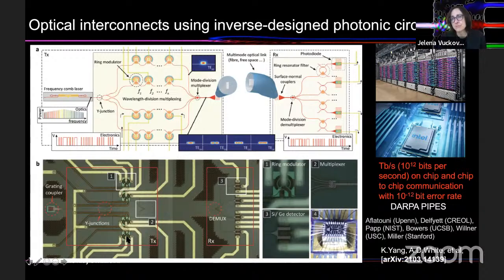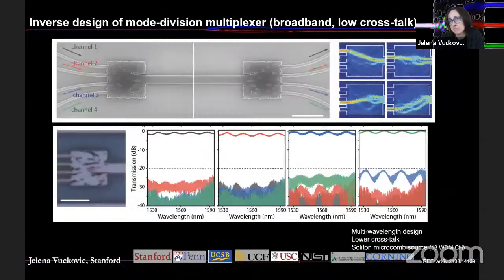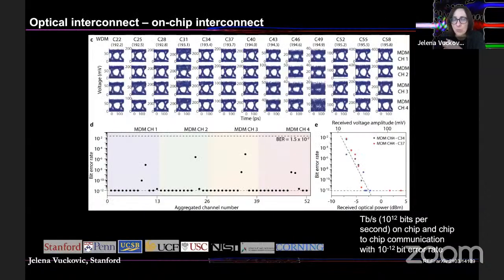But there have been a lot of bottlenecks in terms of building components for this, but we designed them with inverse design. And what is shown here is a component where you can convert different single mode waveguide inputs to different spatial modes at the output in a very small footprint of 6 by 6 micrometers. So that's what we call a mode division multiplexer or demultiplexer. And these are experimental results of this structure. They're extremely broadband so that they can accept all the different channels from the frequency comb, and they have excellent properties as theoretically predicted. And I'd just like to point out that these structures all look very much alike, like the one shown here and the one behind me, but they have very different functions. They're very different in operation, and these patterns are designed by this sophisticated algorithm.